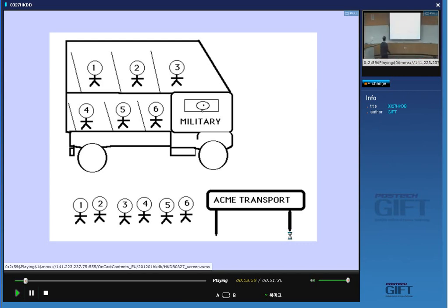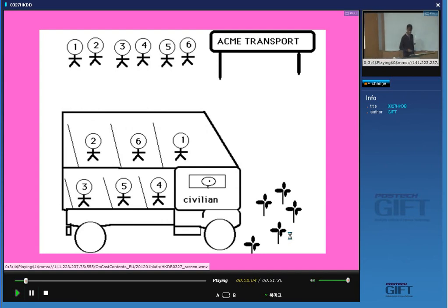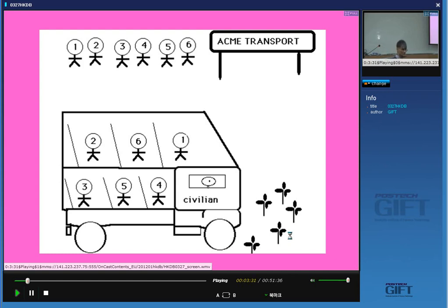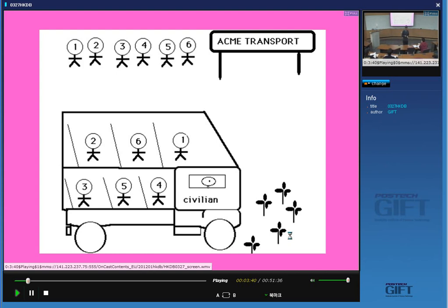Now imagine the second scenario where we have a queue of civilians waiting at a bus stop. The bus arrives and they rush on in an uncoordinated manner and go sit next to people they want to sit next to, even though the positions in the queue are different. So we've lost all correspondence between the queue and the positions in the bus, and in that process we've minimized strain energy. But this requires a chaotic movement of atoms, which means it must happen at a sufficiently high temperature.